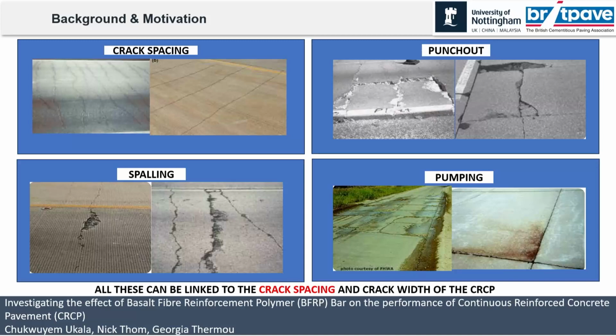But we know concrete, with loss in moisture or temperature changes, will always shrink, and we expect some cracks to take place, which therefore leads to some of the crack distresses we may encounter. Those cracks will lead to some crack spacing in the concrete, which will be kept regular as a result of the longitudinal reinforcement which we have embedded in the concrete. We try to keep the crack spacing or the crack width at very tiny minima to allow for long range performance. However, with deterioration comes more distresses, mainly punch out and spalling.